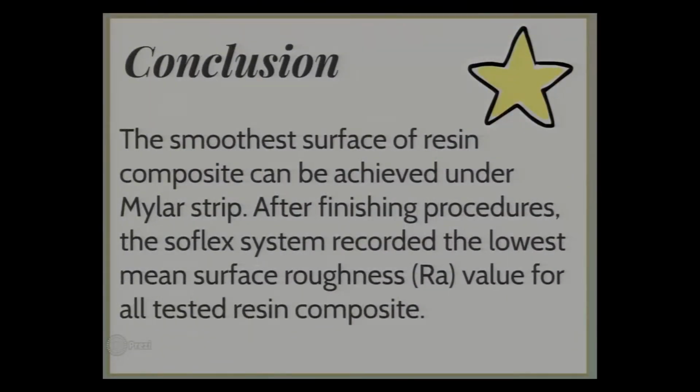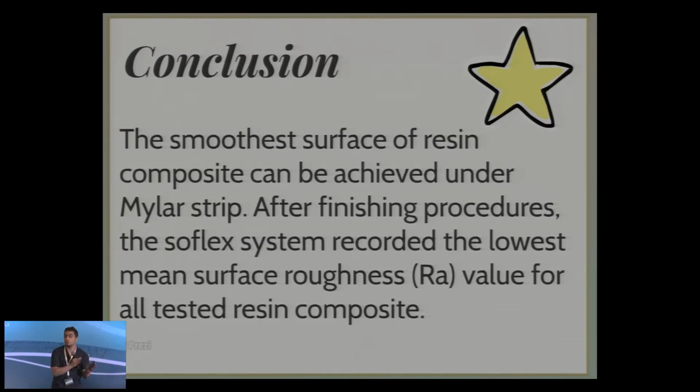The conclusion of our study: the smoothest surface of resin composites can be achieved under the Mylar strip, the control group. But when comparing the three polishing systems after finishing procedures, the Soflex system recorded the lowest mean surface roughness value for all tested resin composites.